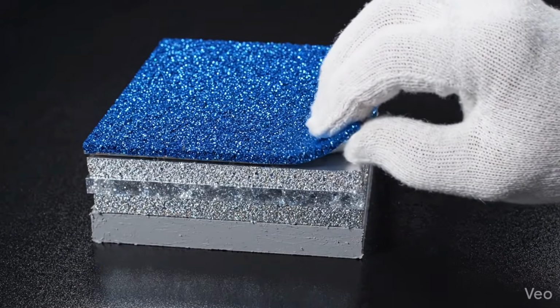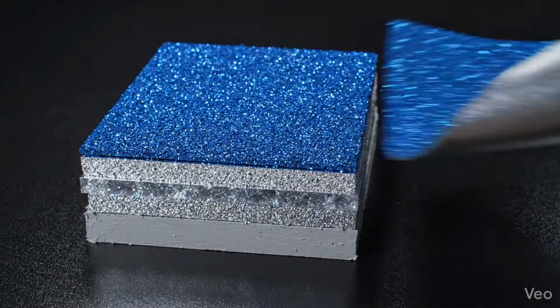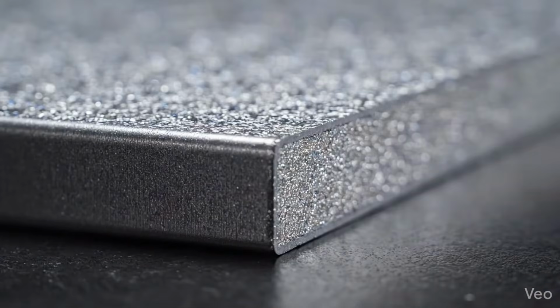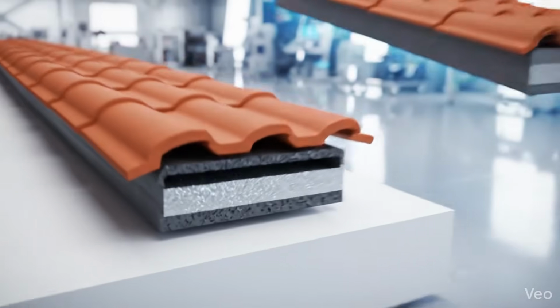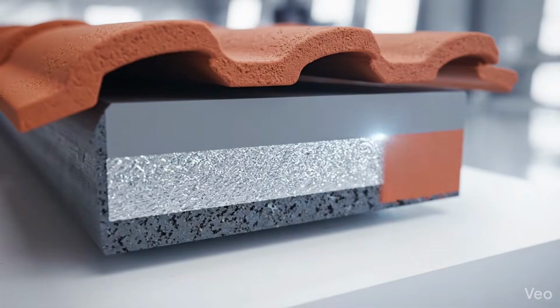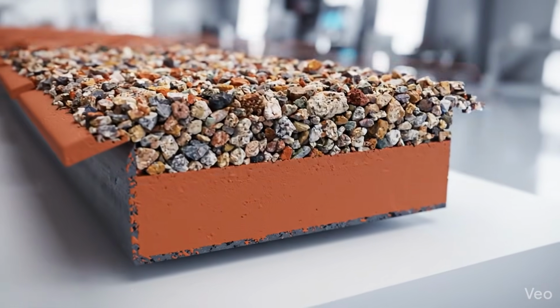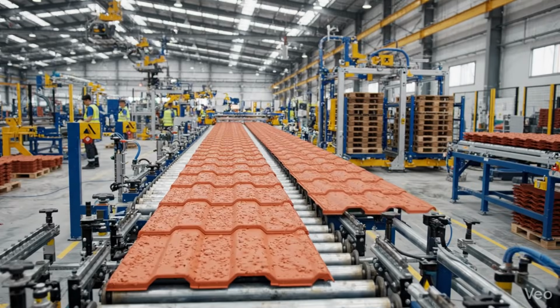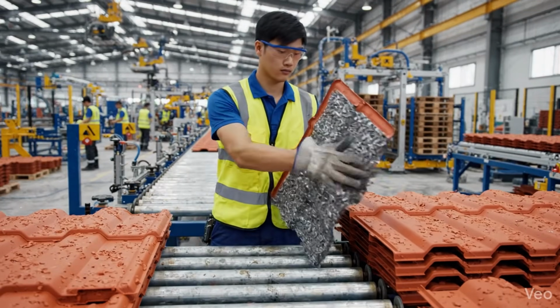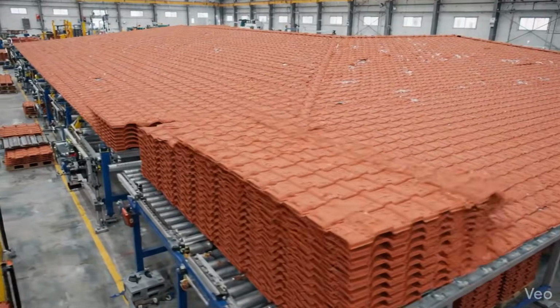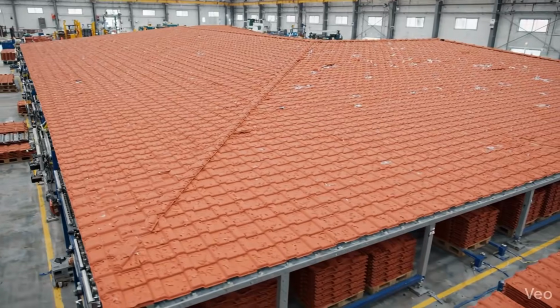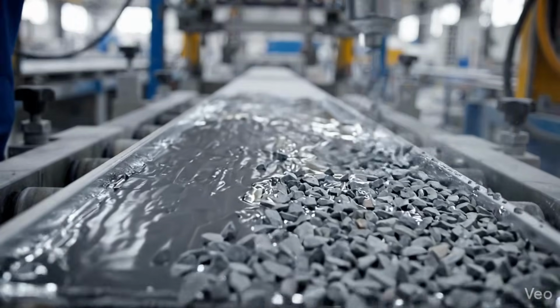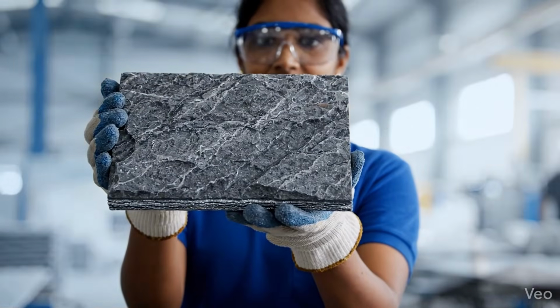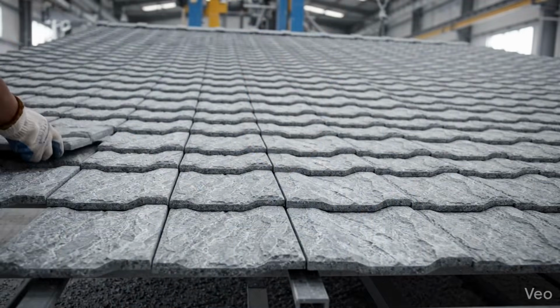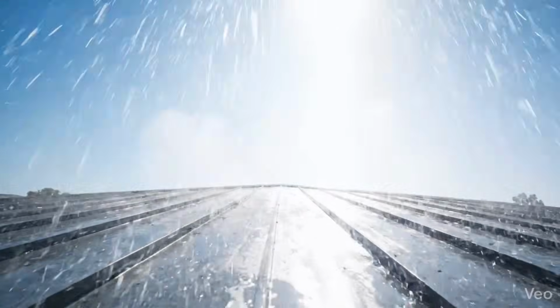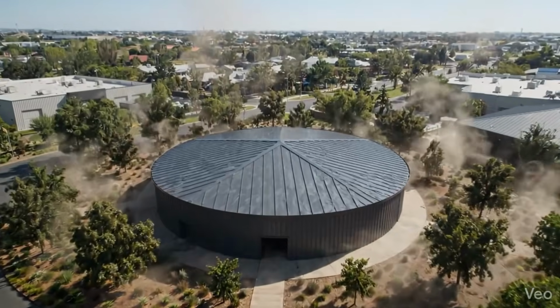It depends on an architecture of layers. Low-carbon steel to provide structure, galvanized or a zinc coating, an alloy of aluminum, zinc, and silicon to prevent the progression of corrosion, chemical treatment to ensure adhesion, priming to seal and connect, final finish to resist weathering, ultraviolet light and wear. When all of this is manufactured correctly, the tile ceases to be a simple thin sheet and becomes a long-lasting multi-layer system. This is why it can surpass many clay tiles in certain contexts.